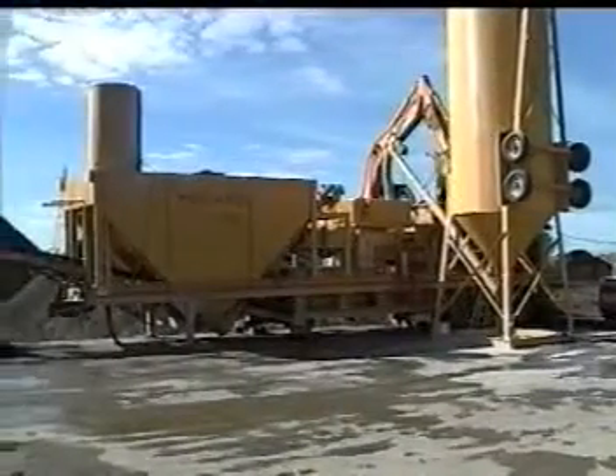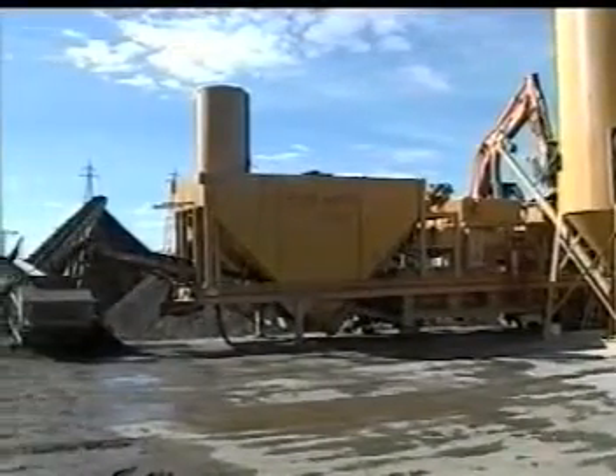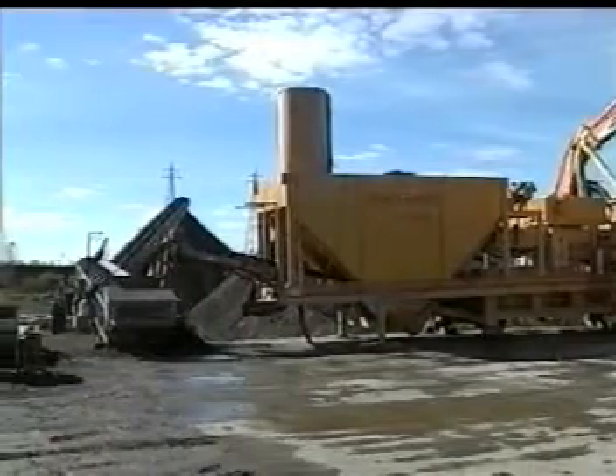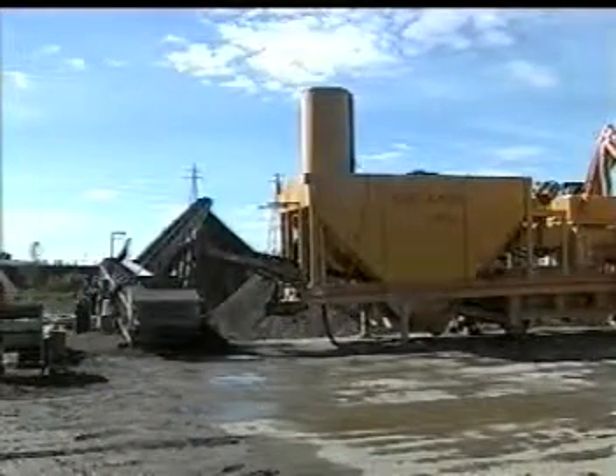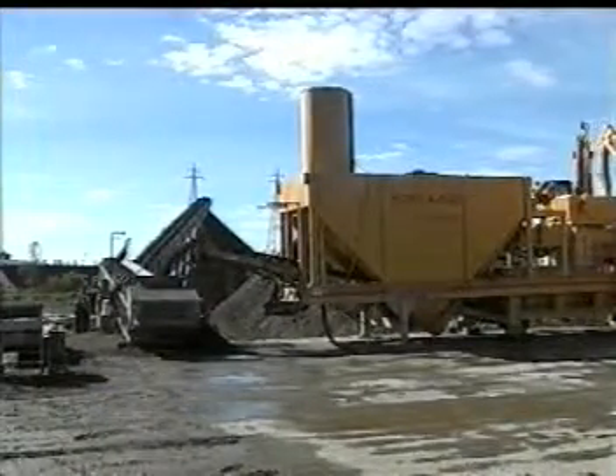Birco is prepared to let the results speak for themselves. The Birco stabilization process reduced leachable metals to levels well below the detection limit of the laboratory equipment used for this analysis. Prior to stabilization, cadmium was measured at 1.2 milligrams per liter. Post-stabilization levels were less than 0.05 milligrams per liter. A 98% reduction of leachable cadmium was achieved.